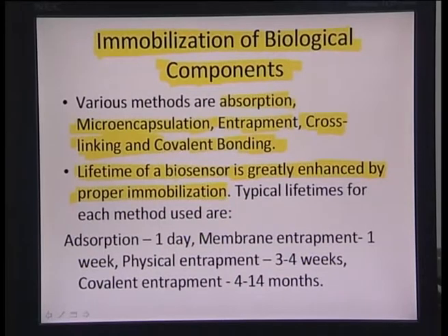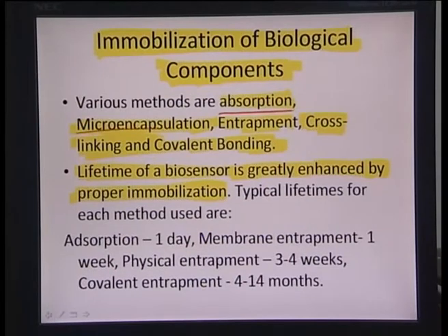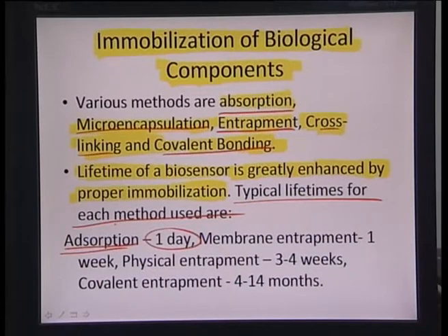So, based on the particular immobilization method from this range of methods that I have stated just about a minute back, adsorption, microencapsulation, entrapment, cross-linking or covalent bonding, the typical lifetimes of biosensors also vary a lot. For example, in the case of adsorption, this is only about a day or so. Adsorbed substances really do not stay very long on a surface, and they are prone to desorbing based on change in the partial pressure of the atmosphere in which such a surface would be kept.